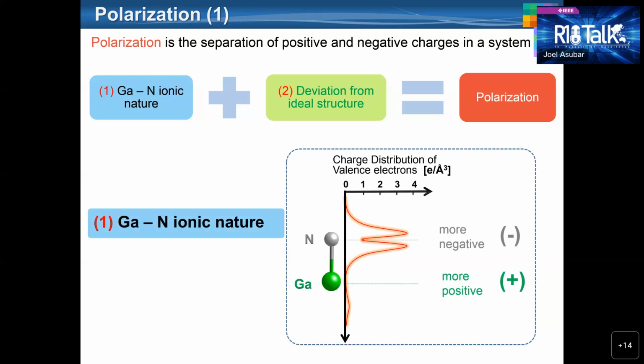First, let's talk about the gallium nitride bond's ionic nature causing polarization. The gallium nitride bond is strongly ionic in the sense that the electron probability density is greater in the vicinity of a nitrogen atom, which means that electrons spend much longer time near the nitrogen atom than near the gallium atom. And this makes the nitrogen atom somewhat more negative and the gallium atom somewhat more positive.